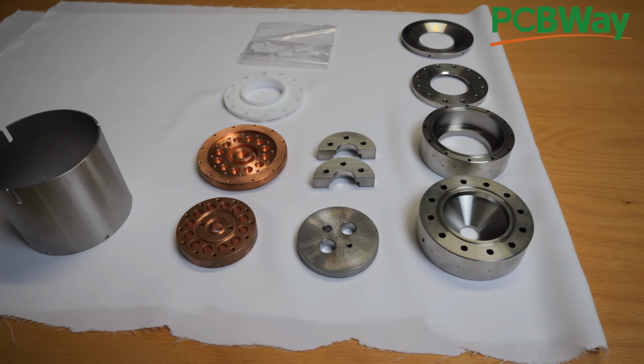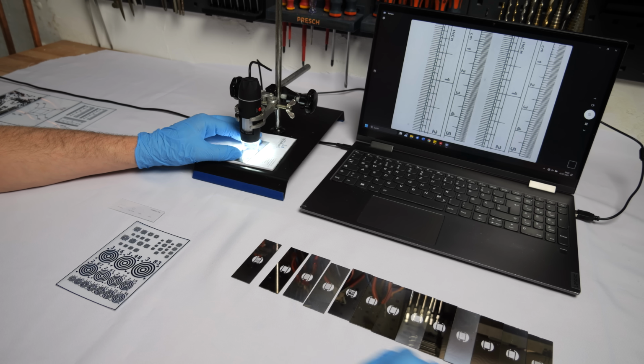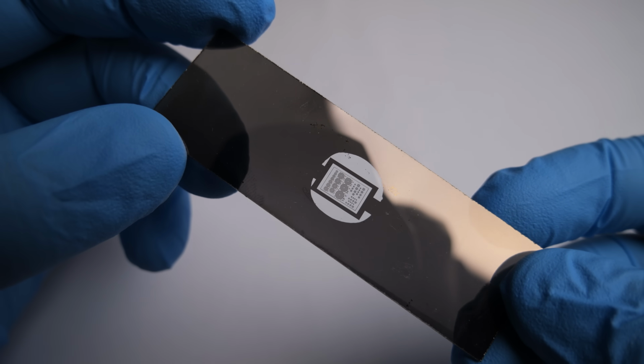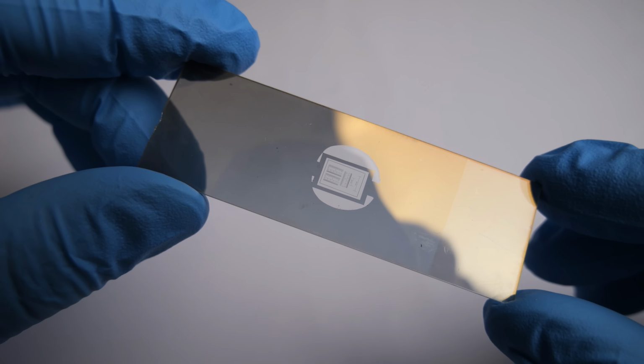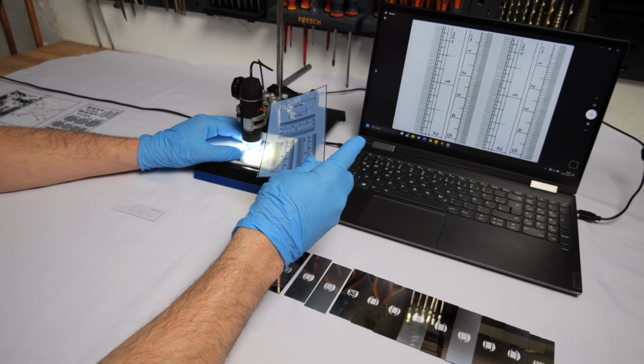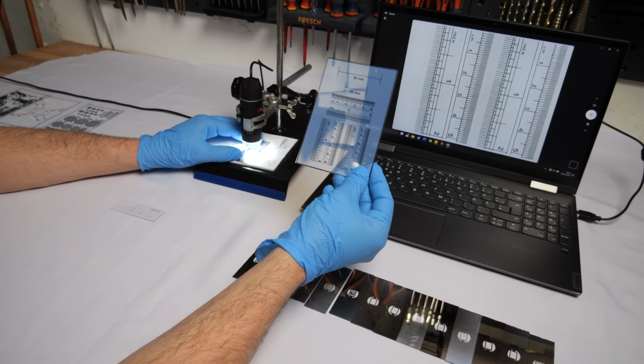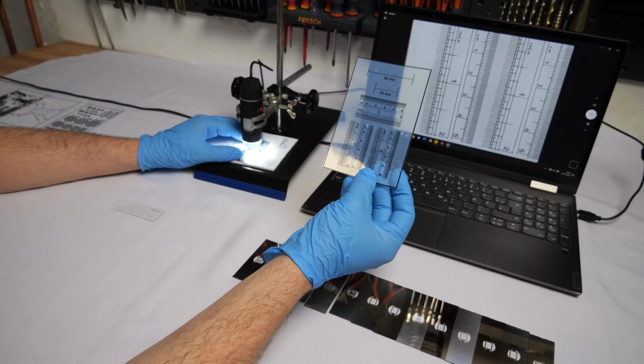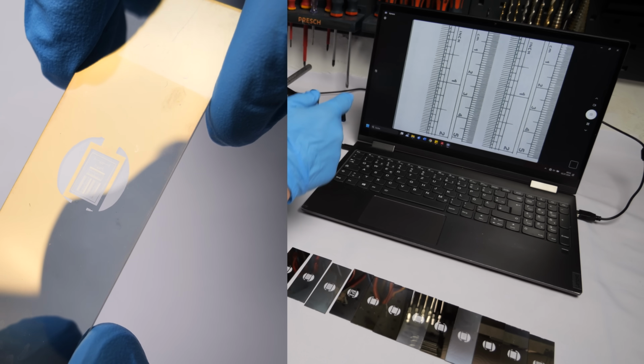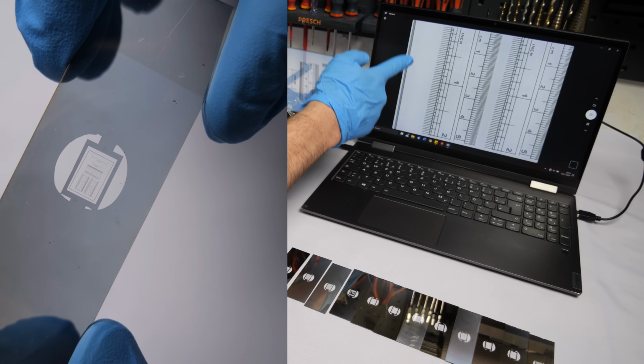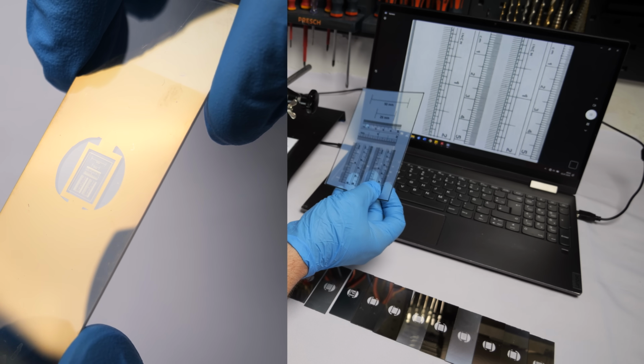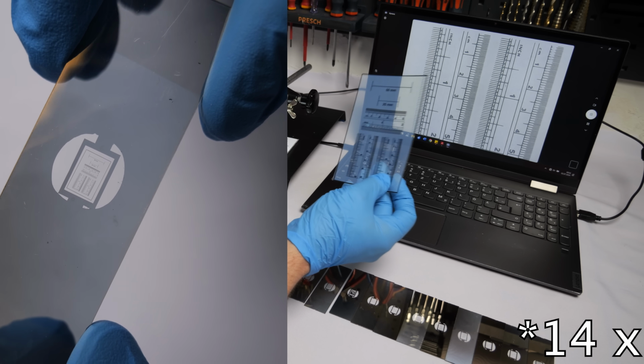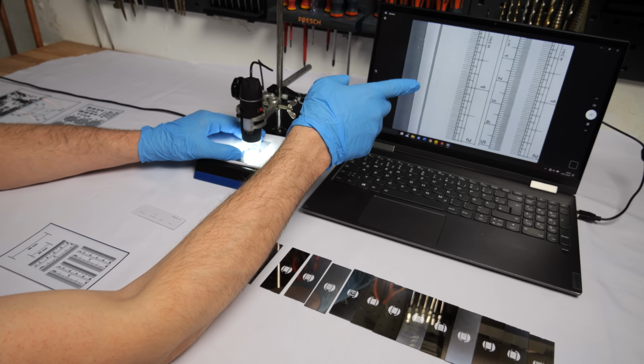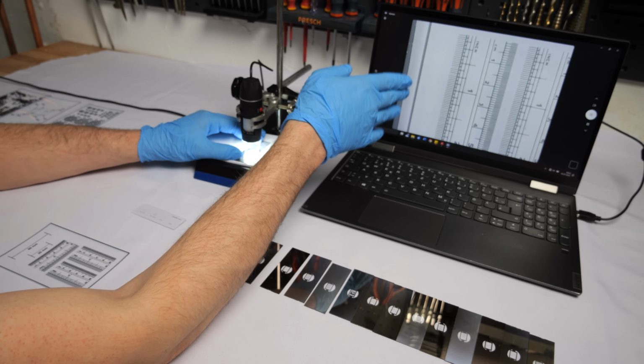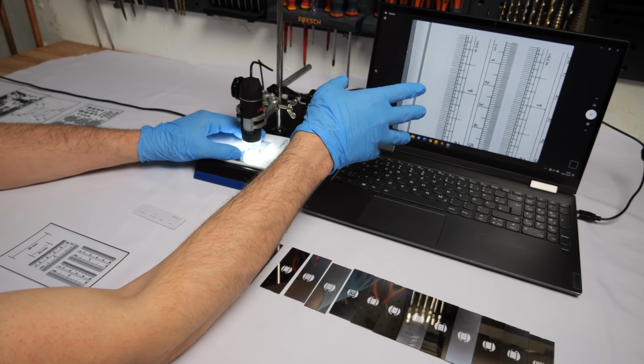And now to the actual results. By now I've made a lot of test pieces, those are just a few of them, and I've optimized the process to a point where I get good and repeatable results almost every time. On the screen right now you can see the structure created with this mask right here. The dimensions on the mask are accurate, and by measuring the dimensions of the structure in titanium, I was able to determine that I'm getting an approximately 15-time reduction in size. And by measuring the line thickness, I determined that I'm getting a resolution of approximately 20 micrometers.